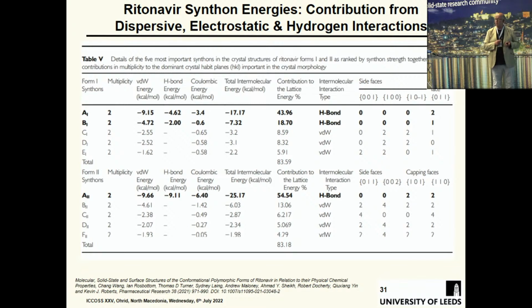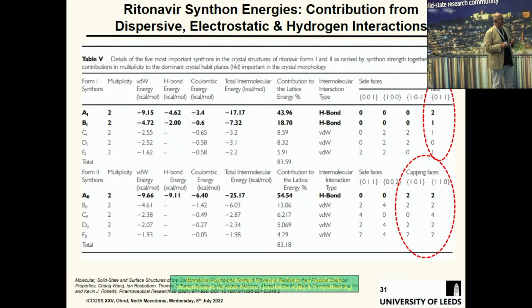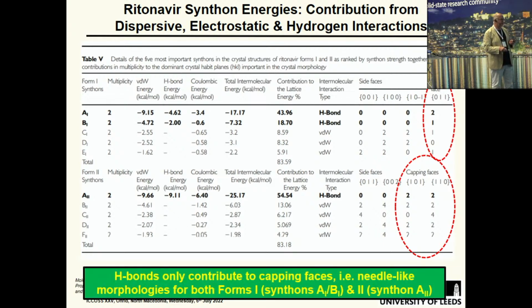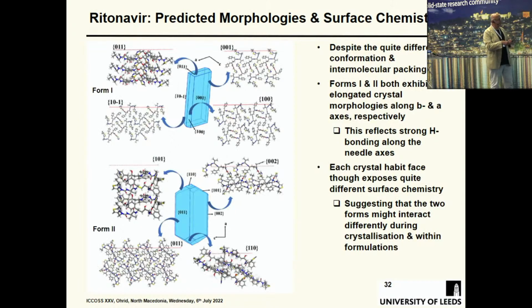So you can know just from this analysis that this will be a needle-shaped crystal, and the needle axis will be dominated with hydrogen bond interactions, and the sides of the needle will be van der Waals interaction. That's very important when you're choosing a solvent. Sorry, I've highlighted those. So hydrogen bonds only contribute to the capping faces, and that explains the needle-like morphologies for both forms. And here, this is a classic analysis you'll see in a lot of our papers.